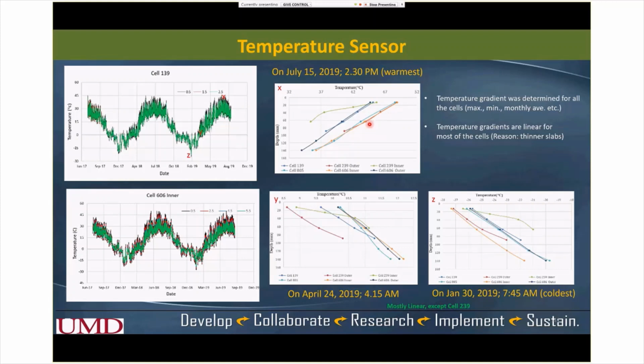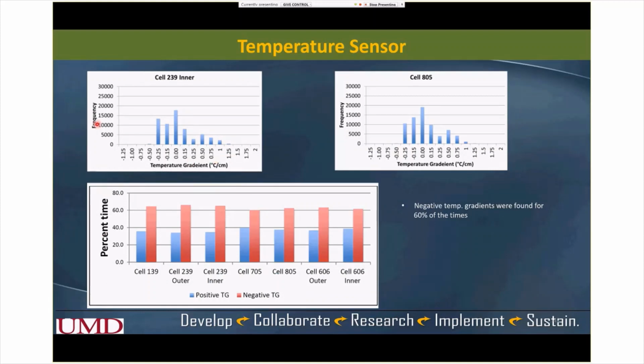It's not like 12 inch. So the gradient is relatively linear. You can see the gradient is relatively linear. For one particular slab, and I do not know the reason, cell 239 sensitivity did not show, but if we take out these particular results, it's again probably linear. We calculated the temperature gradient and plotted the temperature gradient and frequency. These data help us understand the key temperature gradients, and we also compared negative and positive temperature gradient. We saw the pavement experiences negative temperature gradient 60% of the time, meaning the top remains cold and the bottom is hotter.